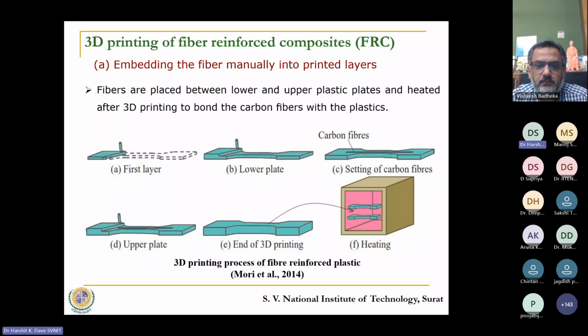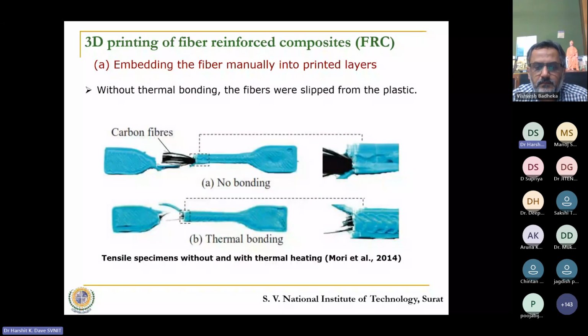The investigators have also tried to check the effect of heating, the post-processing heat treatment, on these parts that are created. And this has come up with a very interesting observation. When the part is directly taken for tensile testing after printing, it has been observed that the bond between the fiber and the polymer is weak. So you can see from the figure that at a certain particular value of strength, the polymer breaks. The polymer breaks distinctly, and we see that the fibers do not break. They come out from the other portion of the polymer part.